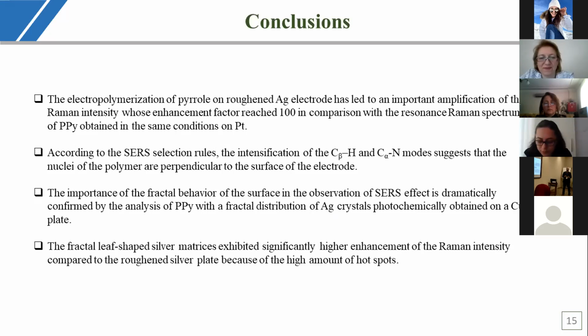The importance of the fractal behavior of the surface in the observation of SERS effect is dramatically confirmed by the analysis of polymer with a fractal distribution of silver crystals photochemically obtained on a copper plate. And finally, the fractal leaf-shaped silver matrix exhibited significantly higher enhancement of the Raman intensity compared to the roughened silver plate because of the high amount of hot spots.